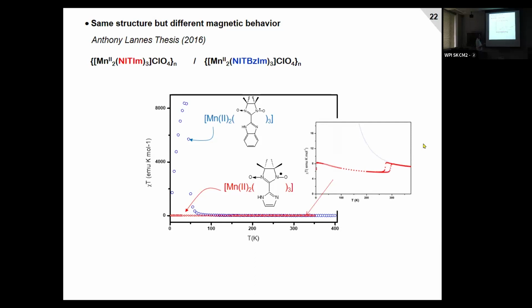But when we look in more detail at the film, we see that we have here some hysteresis loop, not in the magnetization, but in the magnetic susceptibility. And when we saw this, we were thinking that maybe we have valence tautomerism. So what is valence tautomerism? Valence tautomerism is the redox isomers. These are compounds that are isomers that could exist with different redox states.